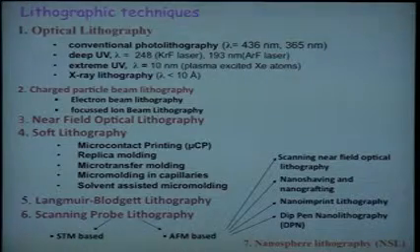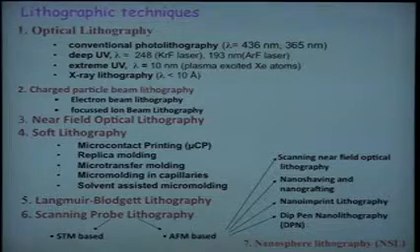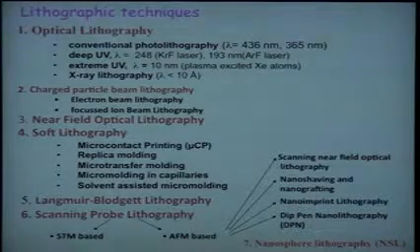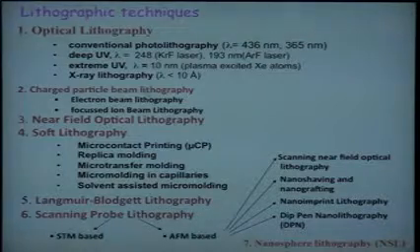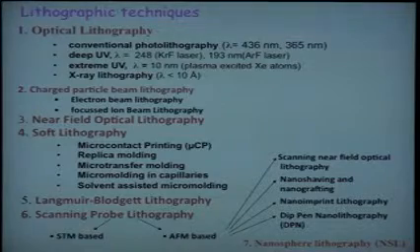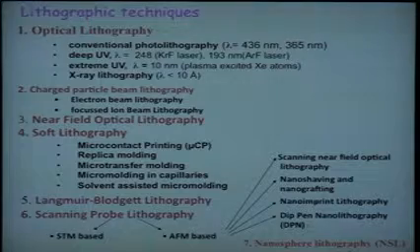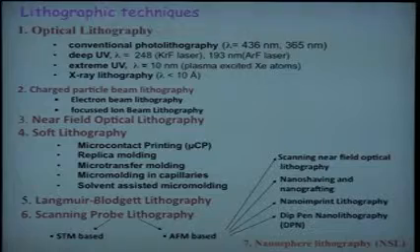We will be taking some examples of that kind, but in relation to AFM we do more, and in the AFM you can actually mingle light with the atomic force microscope. This is the best tool to deal with. In fact, if you have an optical fiber itself turned into an AFM tip, and the fiber itself is the light pipe, then you will have the light emanating out. Anyway, you take the AFM tip pretty close to the substrate in order to sense force. So there you can use the optical field, and that is not far field but near field, wherein you are essentially free of the diffraction limit, and you can actually achieve much higher resolution patterns.